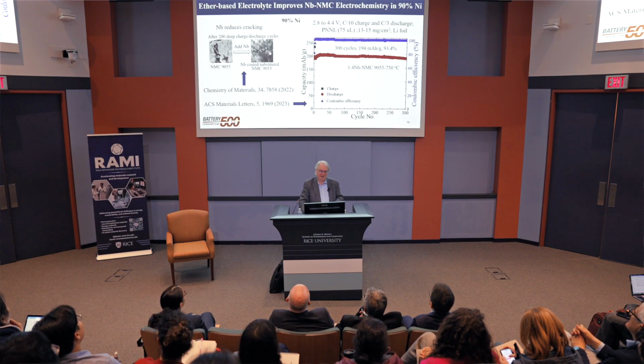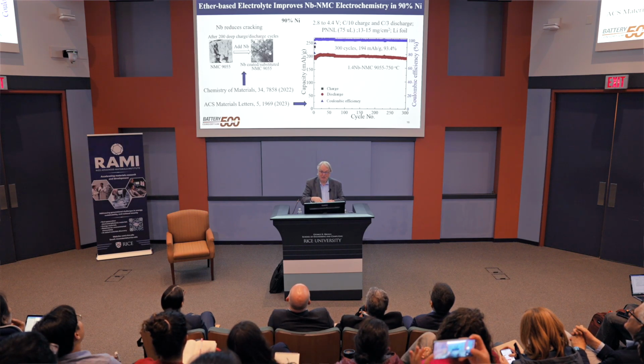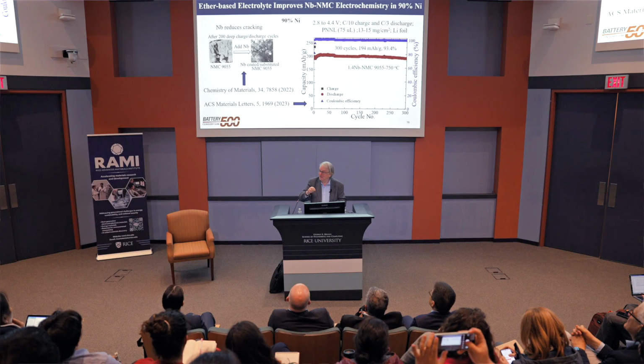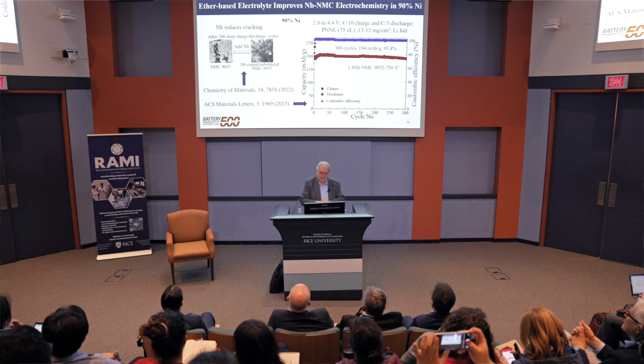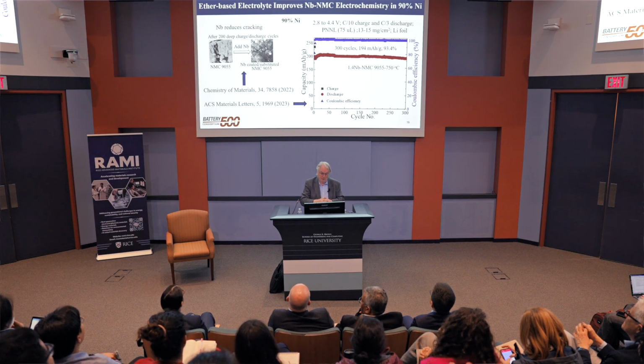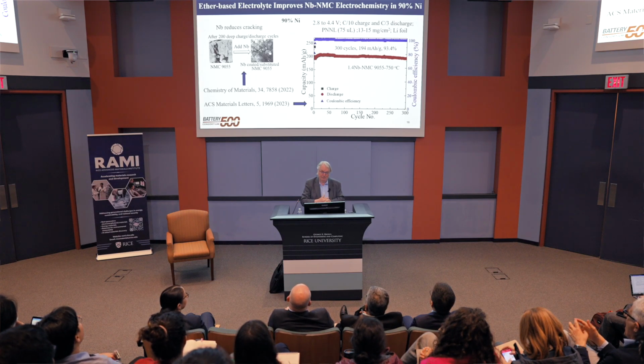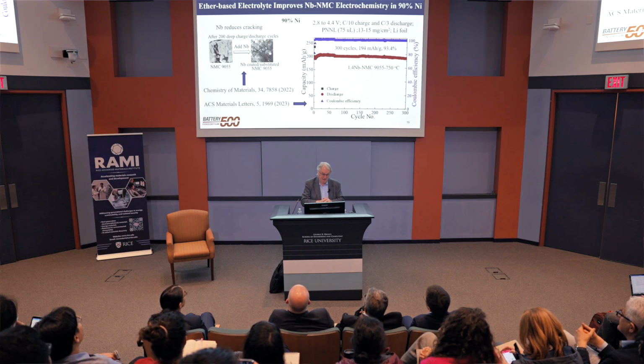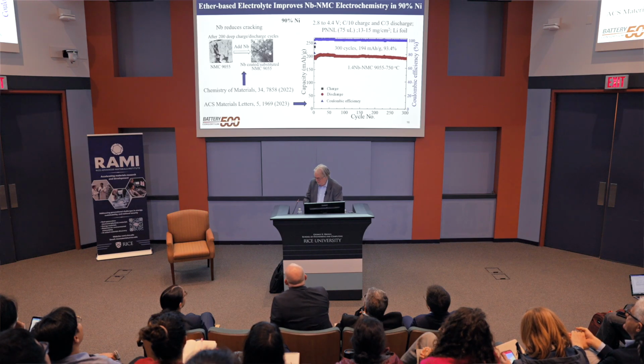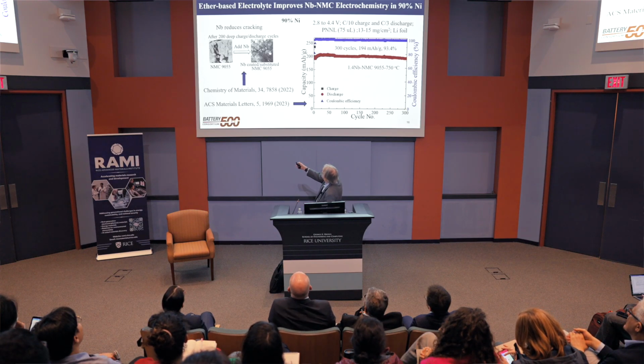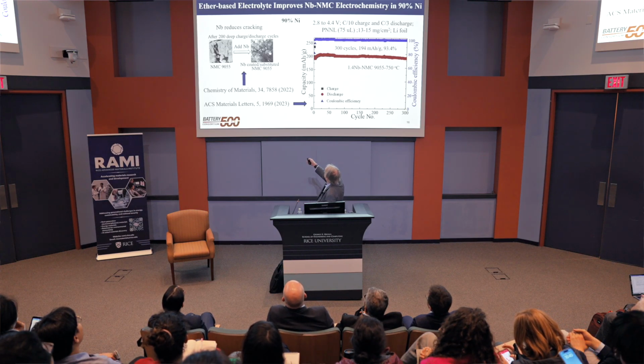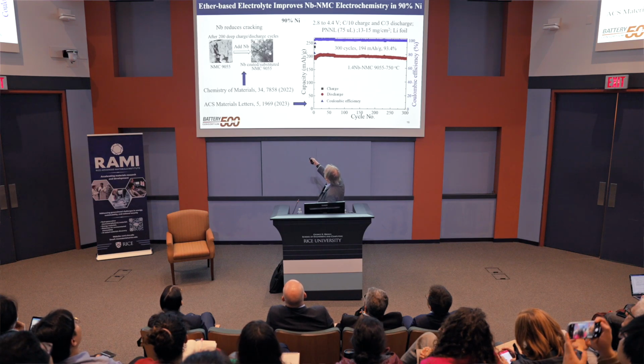So we then said, okay, on the surface it helps, so let's put the niobium on the inside. So now we've gone to 90% nickel, extremely reactive material. And by putting niobium into the lattice, again, this is just over 1% niobium, what it does is stop the cracking of these NMC materials. You can see the large cracks here for the untreated material. There are little cracks in the coated material.